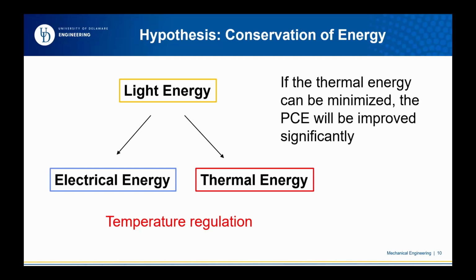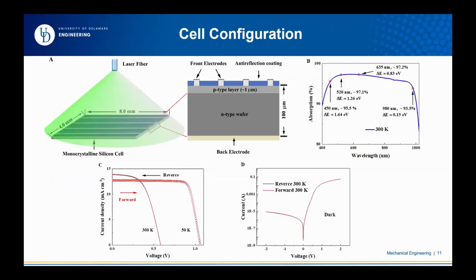So this is true for all. We looked at the literature and found that nothing like that happens. But we found that if we go further, to much lower temperature, the scenario changes. This is based on another piece of our research. We found that for silicon, if you go down to about 10 Kelvin, the mobility of the charges increases by 2 to 3 orders of magnitude. With mobility increased, certainly you can separate charges very easily and very quickly, right? In that case, you might increase the efficiency. So that was the initial idea. We think, okay, let's try silicon, and go down to quite a low temperature. We don't stop at 200 Kelvin. We go further, to just a few tens of Kelvin. So we found these new results.